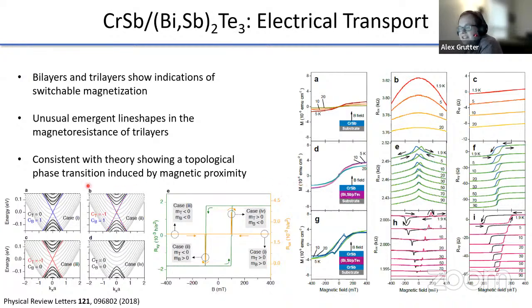And theoretical calculations by Genyin demonstrate that you should, at least theoretically, be inducing a series of topological transitions that alter the surface state as you go through the hysteresis loop, and that explains this anisotropic switching behavior in the longitudinal magnetoresistance.